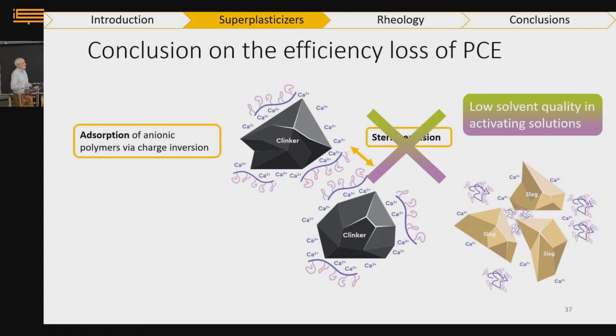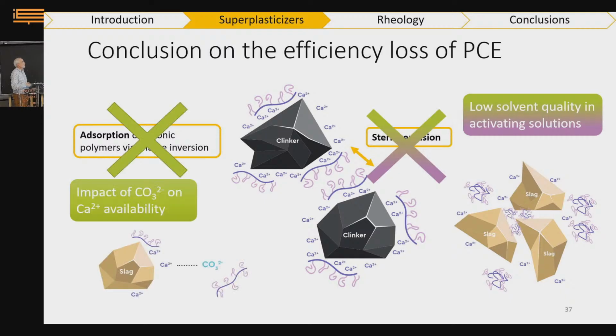So to summarize what I just said, the quality of the solvent is something important that is schematized here, but you see how the polymer is symmetrically shrunk on itself. This is something that has to be taken into account to understand why, and in designing polymers to fluidify alkali activated paste. But this is not to say that adsorption doesn't play a role. We have seen with carbonate that it also is very important. But I really want to insist on the fact that this has been, in my opinion, too much overlooked in the literature. People think only in terms of adsorption or of solubility, salting out, soluble, not soluble. But there is this in-between where it's still soluble, but not as efficient as a dispersant.